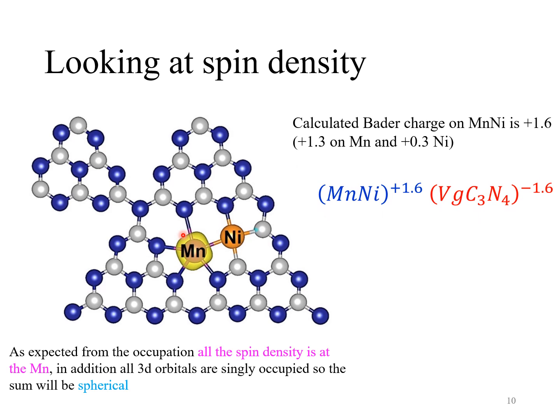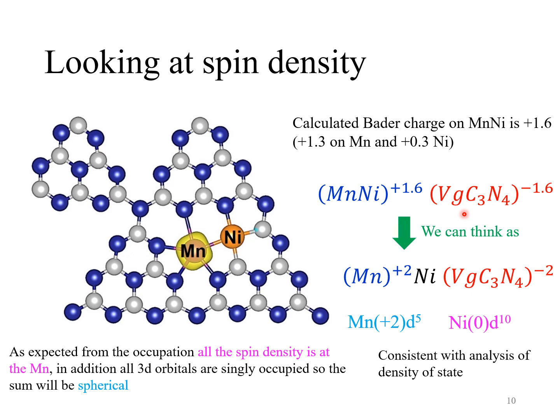We also looked at the calculated Bader charge and found that nickel manganese, this transition metal, has +1.6, while the N-vacancy graphitic carbon nitride has -1.6. We can think of this as +2 manganese, matching the D5 occupation, 0 for nickel, and 2- for this N-vacancy graphitic carbon nitride. So this is all consistent with the analysis of the density of state.